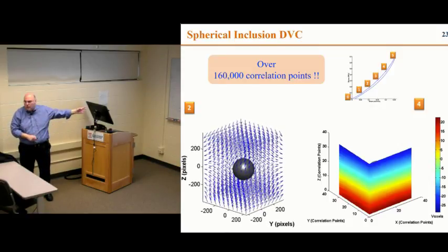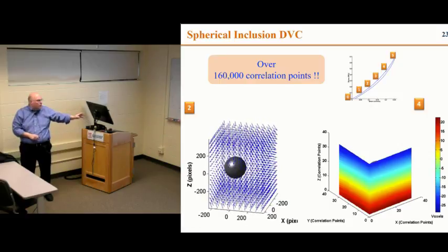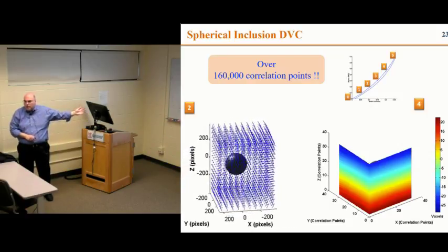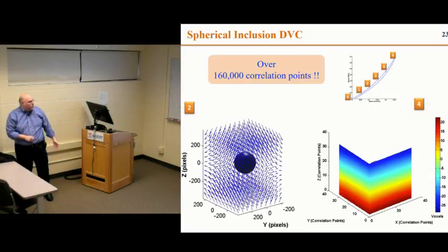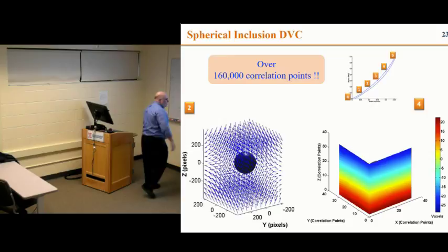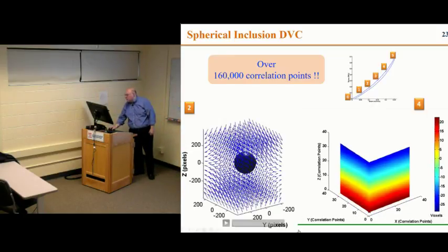I'm not showing you that. This is every 10th or something. I don't even remember. It's a very, very small subset of the amount of data we have. So these are not finite element simulations. They may look like it when you plot them, but they are experimental measurements. These are quiver plots that show you the entire displacement field, and you can get contour plots and so on. These are similar to the contour plots I showed you before. They're displacement, not strain, but now it's varying.